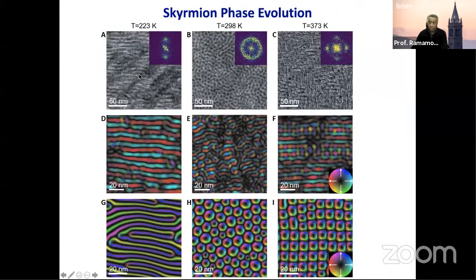Okay, now what we've been doing in the last year or so through coronavirus is looking at phase transitions in the skyrmion lattice. And it turns out that if you go to very low temperatures, these skyrmions will start to become like snakes, and we call them serpentine patterns. Or the students here, they call it the Cheetos pattern. Cheetos is that snack that American kids like to eat. That's what it looks like. But if I change the temperature, if I go to room temperature, it starts to form bubbles. Through some kind of a Rayleigh-Taylor instability, it starts to form these bubbles. And these are all phase field calculations.